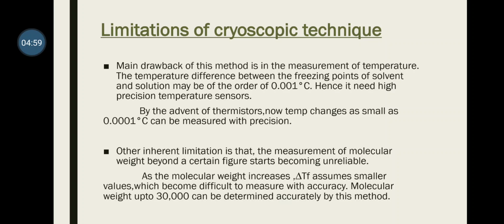And next are the limitations of the cryoscopic technique. The main drawback of this method is the measurement of temperature. The temperature difference between the freezing points of solvent and solution may be of the order of 0.001 degrees Celsius. Hence, it needs high precision temperature sensors. By the advent of thermistors and high amplifying electronic devices, now temperature changes as small as 0.0001 degrees Celsius can be measured with precision.